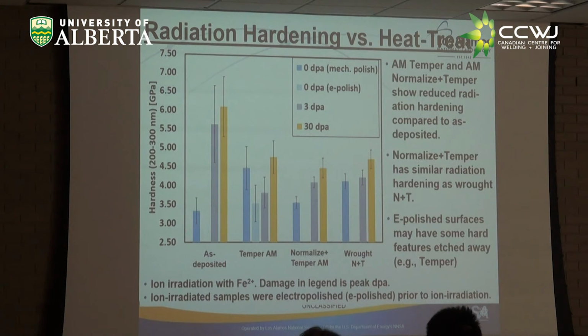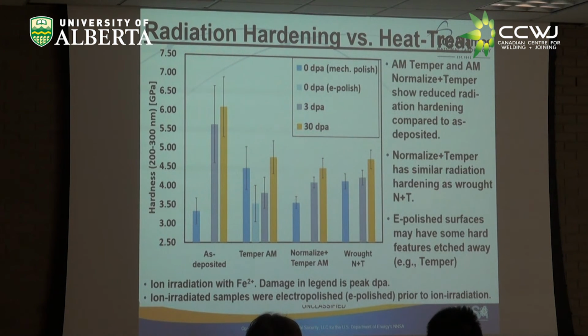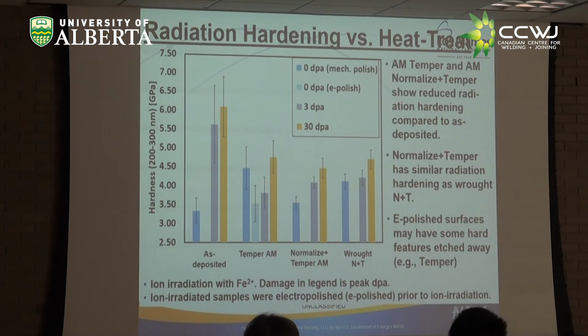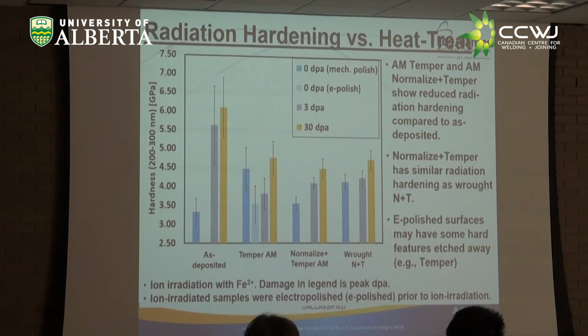at 30 dpa. dpa is an abbreviation for displacements per atom. So atoms that are ion irradiated, the atoms were displaced and moved by radiation damage cascades 30 times and experienced much higher hardening. So they will be much harder, they'll be less ductile, and so their service life will be compromised in this condition. That was for the as deposited.